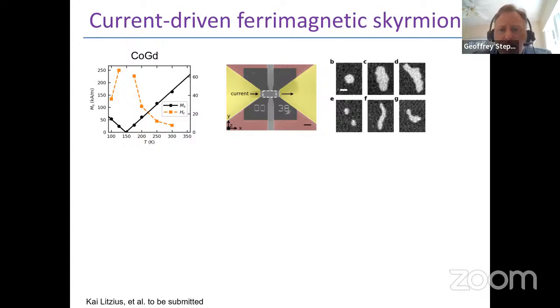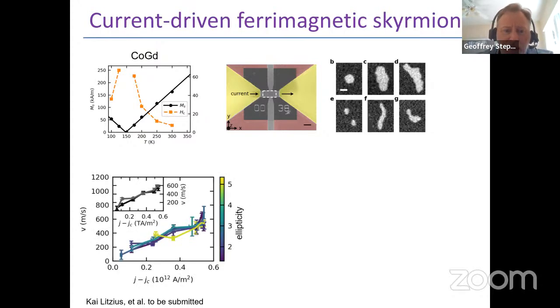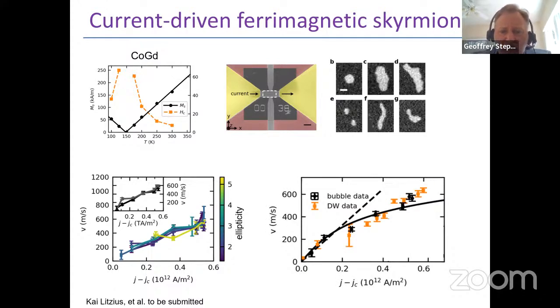But for all of these, the topology is the same. So that's what makes topology interesting. One can distort a skyrmion structurally, but maintain the same topology. And in these materials, we've looked at the velocity versus current. We find likewise that very large velocities, comparable to velocities of domain walls, can be achieved, on the order of several hundreds of meters per second.